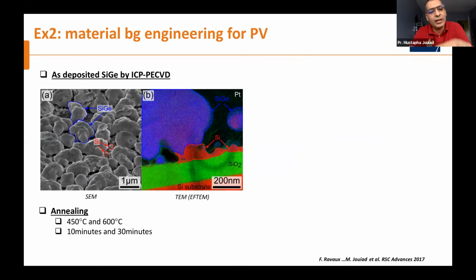I give you the second one regarding silicon germanium. This is a highly desired material in PV, so photovoltaics. What we did, we selected a very easy technique called PECVD, plasma enhanced CVD. This is a very straightforward technique that helps to fabricate silicon germanium very easily. But everything is done after the fabrication, concerning the right heat treatment that we have to apply to increase the crystallinity for silicon germanium and also to lead to different composition.